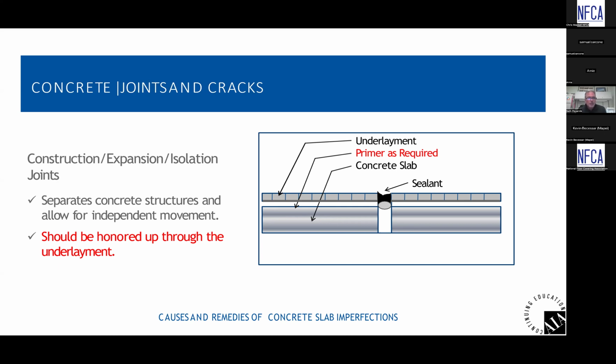Okay, so some of the other moving joints out there: construction joints, expansion joints, isolation joints. It's very common that these are recommended to be honored up through the patching or leveling material, as well as the finished flooring. In the diagram I show here, there's a piece of backer rod in the joint. That joint is honored up through the patching or leveling material, as well as the floor, and should go through the floor covering with some sort of elastomeric joint sealant like a urethane or similar, so that the joint is not only sealed, but any movement that does occur allows the joint to remain sealed.